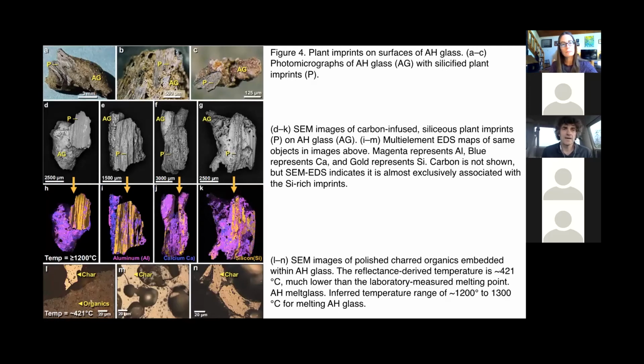So here are some examples of these plant imprinted materials. We can see the optical images on top. The P is a visual indication of where the plant is, and the rest of it is always the Abu Hureyra glass. Then we have SEM images, and once you have SEM, you can do composition. In this case you can color the different parts of the composition: aluminum in purple, calcium in blue, and silicon in orange in all these four images.